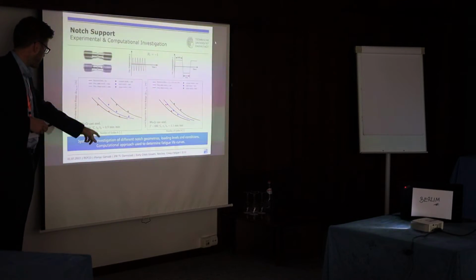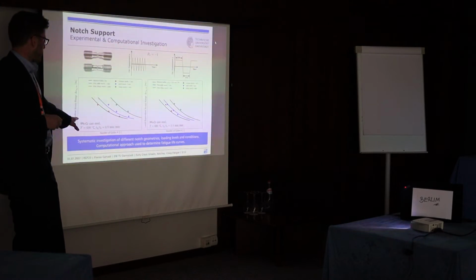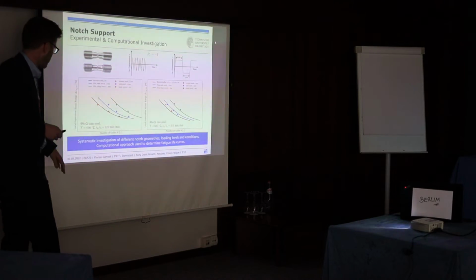And the results are already given here by fatigue life curves. You have the local loading level here on the y-axis and the number of cycles on the x-axis, for a 9% chromium cast steel at 600 degrees Celsius, just as an example here. We investigated a lot of other materials as well.